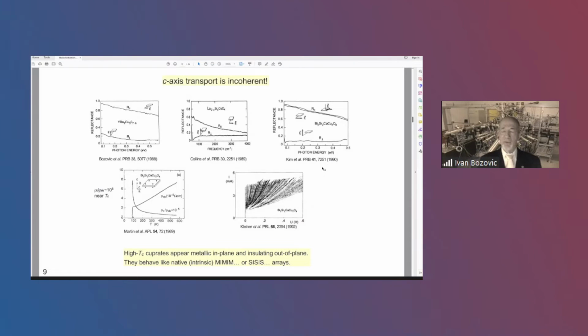All what I was showing so far were in plane properties, but if you look out of plane, things look even more strange. Basically, the cuprates, when you look with the light which is polarized parallel to the copper oxygen planes, they look like metals, maybe bad metals or strange metals, but metallic-like. But if you look perpendicular to it, they look like kitchen salt. They are insulators, strong insulators.